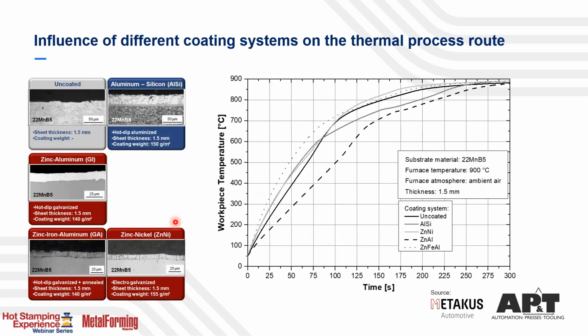Next on the chart here is a comparison between different coating systems. The chart here shows uncoated material, aluminum silicon coated material, and you have zinc coated material. And you see clearly, depending on which coating you use, you have a different heating characteristic on your material. So you need to know in your press hardening process what type of material you use, because this is heavily influencing your thermal behavior when heating up the material.